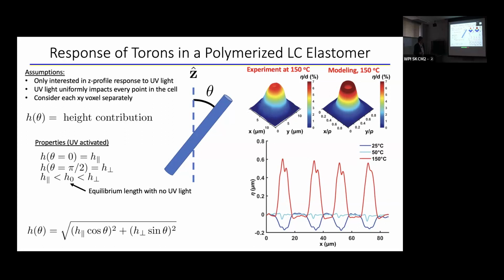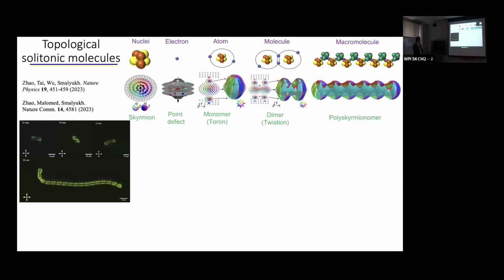So you can see in here, experiment and modeling, they agree quite well. There are some tiny details that are just referring to resolution of the system, right? Because also being able to image that profile is not infinitely perfect resolution that we have in experiment, right? But it's very consistent. You can see not only we capture the fact that, at high temperature, in the place of presence of this topological soliton, we get a mountain, but there is also a little dip at the top of it. And again, we can capture this behavior quite well in experiment.